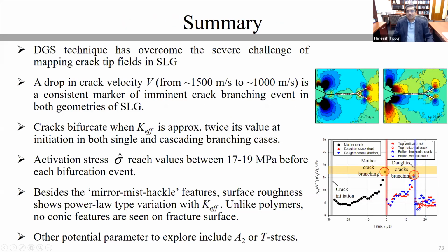So with that, I'm going to summarize this talk by saying that this new technique, digital gradient sensing, has overcome the severe challenges associated with the mapping of fracture in soda-lime glass, particularly dynamic fracture. A drop in the crack velocity from about 1500 meters per second to 1000 meters per second is a consistent marker of imminent branching event in all the geometries that we have studied so far.